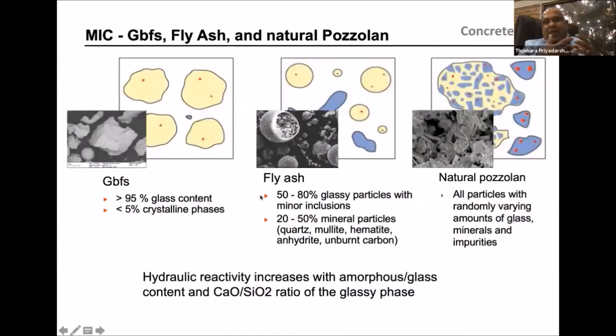So the amount of these materials that can be added into our concrete mainly depends on their chemical parameters and physical parameters. So if you see, slag is like aggregate. So when you add it, of course, the workability goes down. You can see this type of material, if you add it into your concrete, of course, the size can be the same as cement, but when you see from the closer view, it's like aggregate.